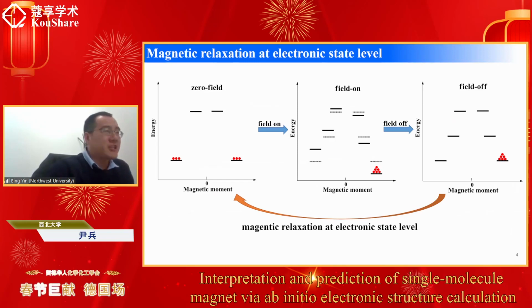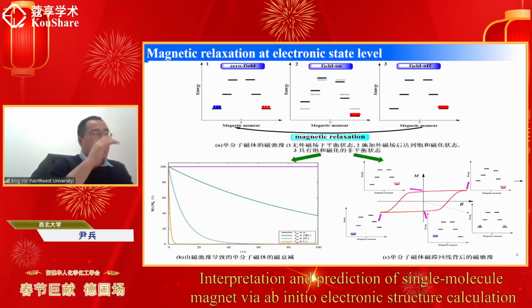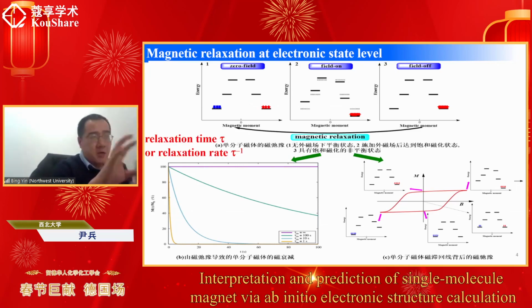And this magnetic relaxation is actually the microscopic process behind the experimental observation of single molecular magnetic behavior, for example, magnetic decay or magnetic hysteresis. And the time scale of this magnetic relaxation process is characterized by the so-called relaxation time or its reciprocal, the relaxation rate. And to find a good single molecular magnet, we need a long relaxation time tau or a short relaxation rate tau minus 1.